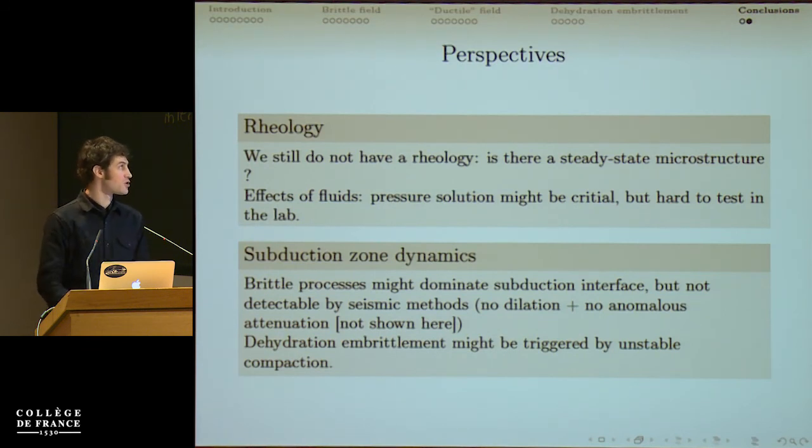So the consequence for subduction dynamics is that brittle processes might still dominate the subduction interface, but they might not be detectable by seismic methods. Again, there's no dilation, and there's actually no anomalous attenuation of these rocks, so we've done experiments separately with Ian Jackson on low-frequency attenuation of antigorite, and it's not anomalous at all. It's a bit weak, but there's nothing special about it. It doesn't dilate, so again, there's no indication of microcracks that could be detectable by Vp/Vs, for instance. And again, the dehydration embrittlement at very, very high pressure might be triggered by unstable compaction of these rocks. Thanks very much.